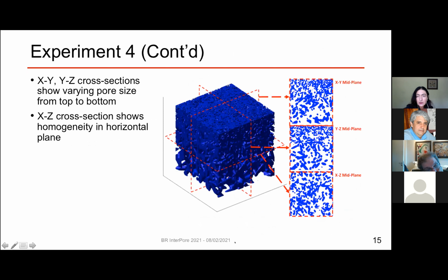This is what that final domain looks like. You see it is much denser at the top, and it has much more void space at the bottom. And the cross sections also demonstrate that. So we see here this cross section and this one do show this gradient. So the top one shows density of solid phase here and going more towards void at the bottom. Same happens here, more solids at the top than the bottom. But if we cut it in the horizontal plane and show it here, it is about the same distribution of solid inclusions.